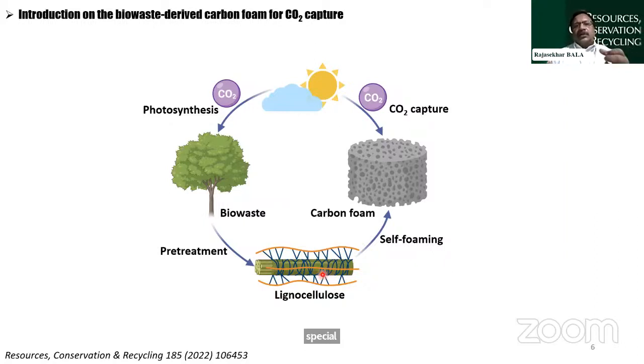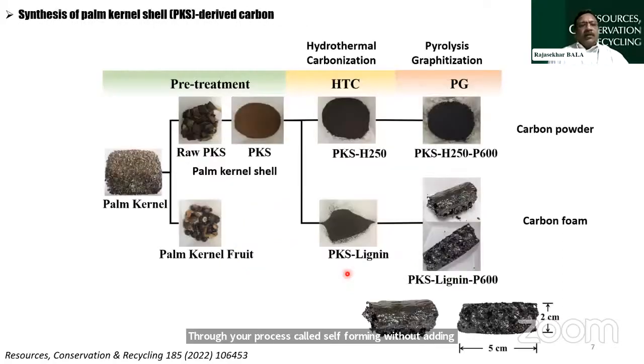So if you look at the tree structure, especially the stem, it is very rigid. The rigidity of the tree structure is a result of the lignin component we have in the biomass. So this is what we wanted to extract, because that has a lot of aromatic compounds and is rich in carbon. If we can extract lignin selectively, you can convert it into carbon foam through a process called self-foaming without adding any chemical reagents externally. This is what we have done.